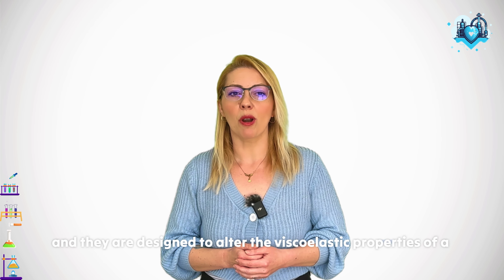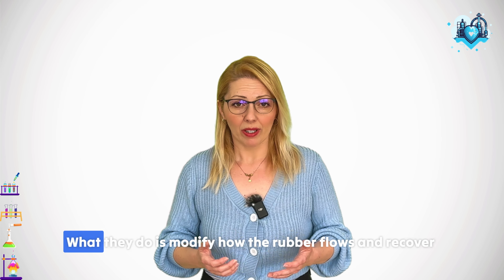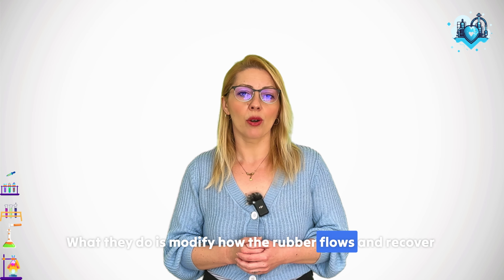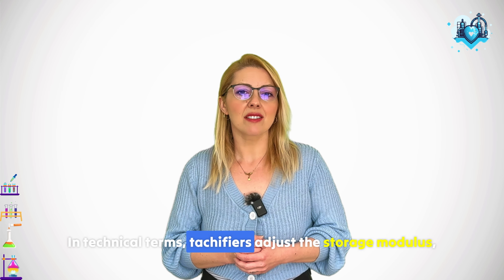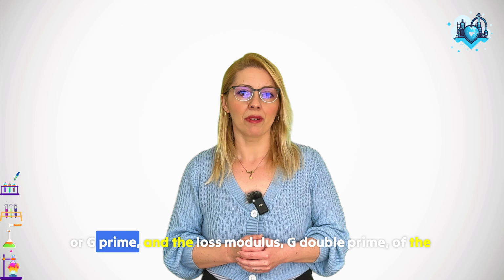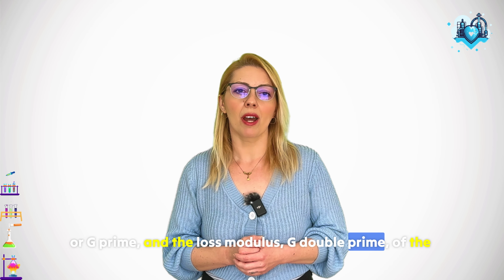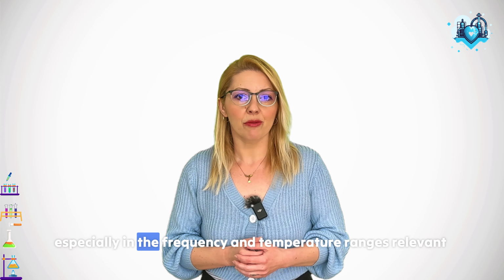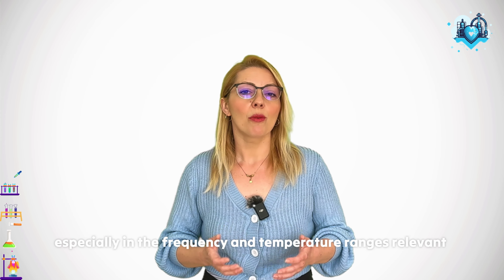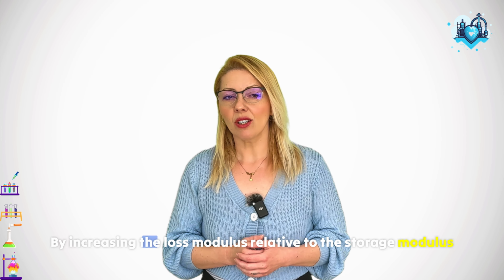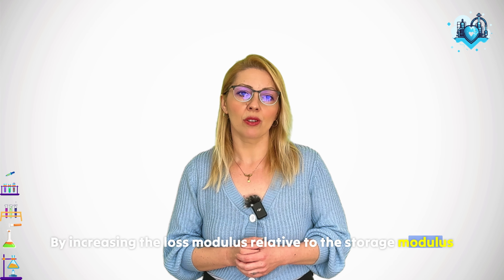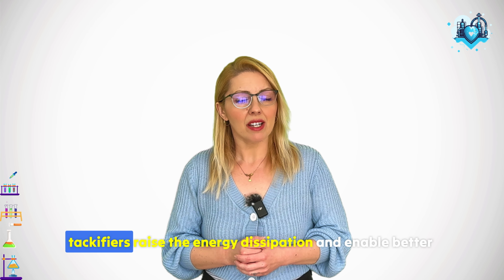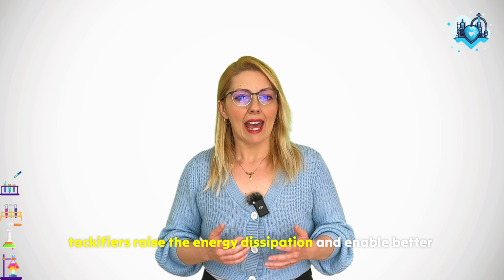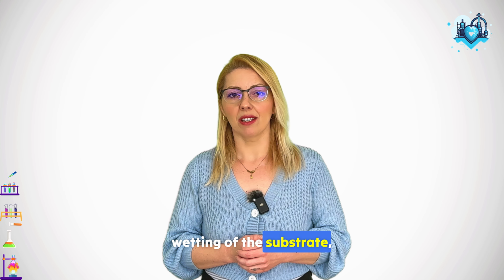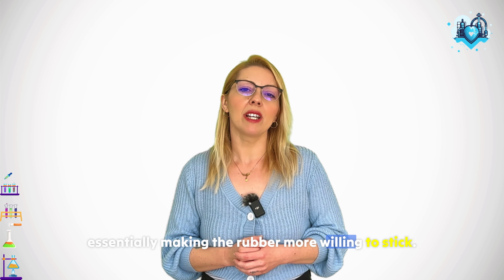alter the viscoelastic properties of a rubber compound. What they do is modify how the rubber flows and recovers under stress. In technical terms, tackifiers adjust the storage modulus, or G prime, and the loss modulus, G double prime, of the compound, especially in the frequency and temperature ranges relevant to adhesion. By increasing the loss modulus relative to the storage modulus in this window, tackifiers raise the energy dissipation and enable better wetting of the substrate, essentially making the rubber more willing to stick.